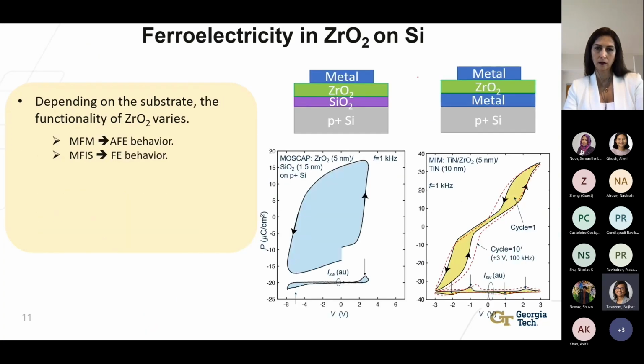So next, we focused our study on the MIS capacitor, which is the metal insulator silicon capacitor. This is basically the gate stack of an FeFET. Now, we saw a very interesting property for zirconium oxide: when it is deposited on top of a metal in an MFM structure, it becomes antiferroelectric. It shows antiferroelectricity, which is this double hysteretic PV loop. However, when zirconium oxide is deposited on top of silicon in an MFIS structure, it becomes ferroelectric and shows a single hysteretic PV loop.